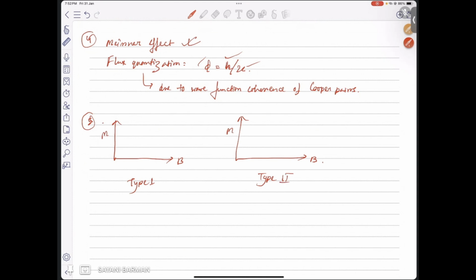So type 1 superconductor, as we already know, is a pure superconductor. They show complete diamagnetism until Hc, right? And after which magnetization drops to 0. So this is 0, B equals 0 here. We can write Bc for critical, and there is this abrupt transition from superconducting to normal state at Hc, right?